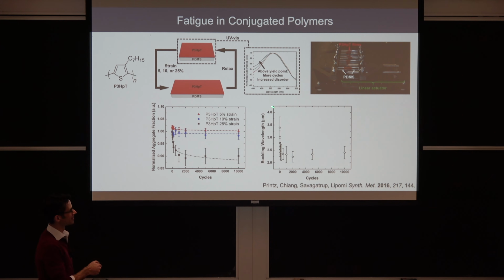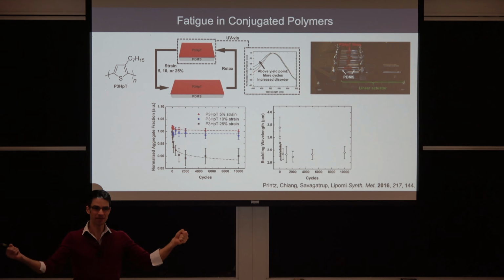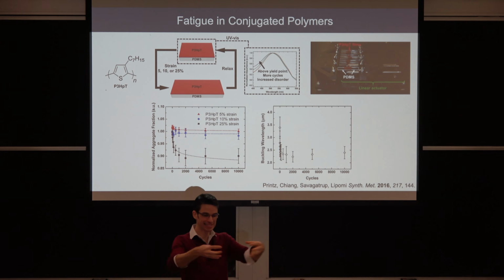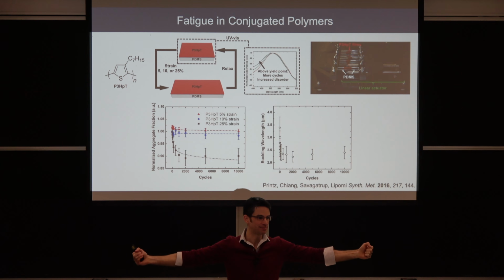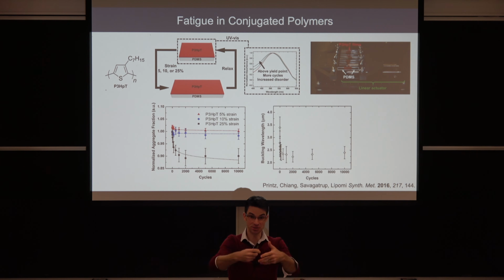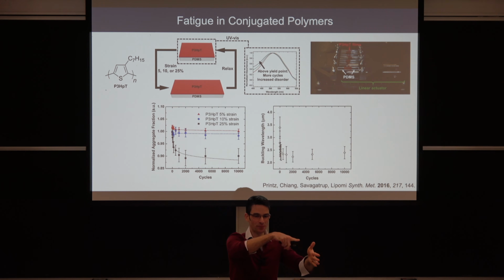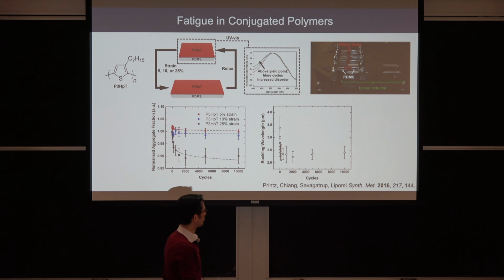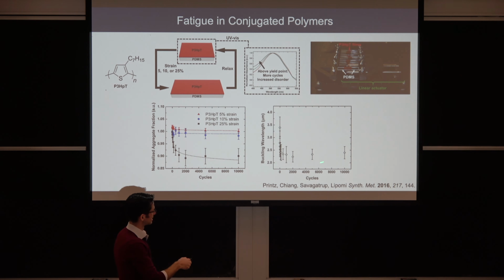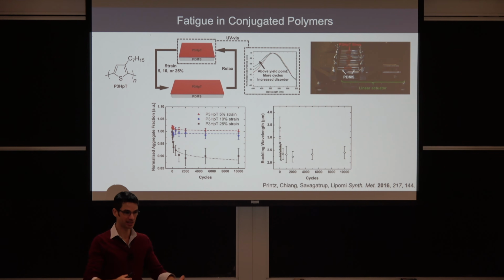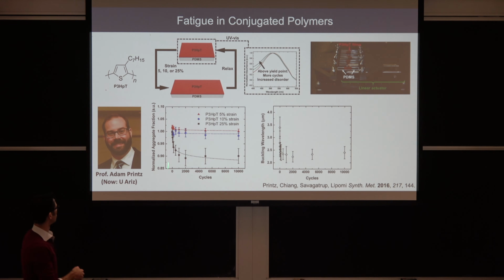Interestingly, the wrinkling wavelength, so if you stretch something and then you bring it back, we've got an elastic slab, then we've got our film on top, and we stretch it. And as we bring it back to equilibrium, since we've stretched the film, it now wrinkles. Now the wrinkling wavelength is actually related to the tensile modulus of the film. So as the wrinkling wavelength goes down, the tensile modulus is actually predicted to go down as well. So we're making this material, we're pulling the aggregates apart, we're making it softer. This work was done by Adam Printz, who's now a tenure track professor at University of Arizona in the Chemical and Environmental Engineering department.